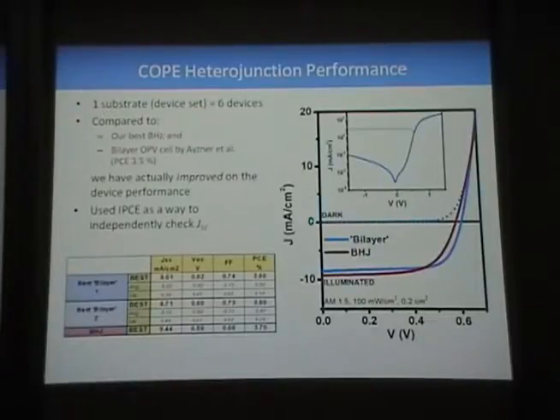On one substrate, or device set, we can make 6 devices. And compared to our best BHJ, and also the bilayer that was reported by the UCLA group, we've been able to improve the device performance. So this shows the JV characteristics of our best bilayer and the best BHJ. And you can see that the fill factor for the bilayer is better than for the BHJ, and the VOC is slightly better. And this is reflected in the device performance parameters shown here. For the BHJ, it's 3.7%, and for the bilayer, 3.8%. It also shows that this wasn't just a fluke, we can do this repeatedly. So that's another device set.